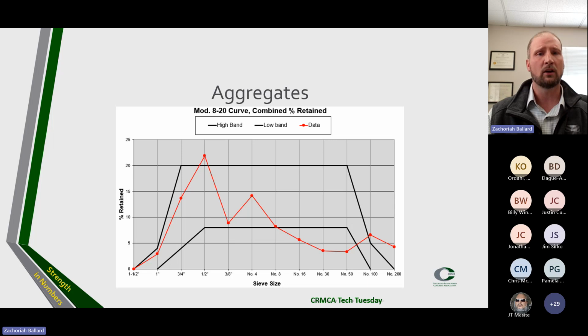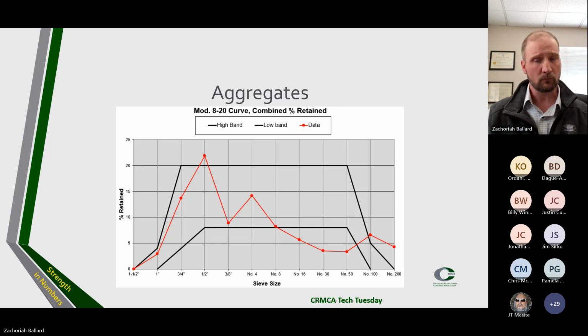We've got our haystack curve, or an individual percent retained chart. This is a method for evaluating the exact distribution of each sieve size on an individual percent retained. The chart easily shows the excess or lacking of sieve sizes of a combined gradation. From experiences, people have specified a maximum boundary of somewhere in the range of 18 to 22% and a minimum boundary of 5 to 12% retained on each sieve. No real research being conducted to kind of prove those limits, but that's what we found has generally worked.